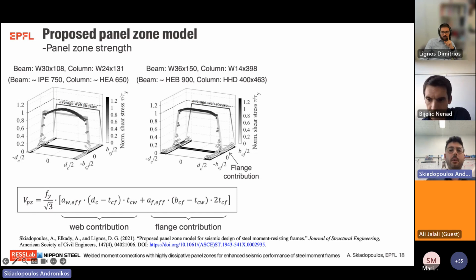Regarding the panel zone shear strength, we looked at realistic shear stress distributions in the panel zone of variable geometries, as characteristically shown by these two schematics on the top left side. What we observed is that for stocky panel zone geometries, the flange contribution, which, as I described before, is disregarded in available models, may be really considerable. Therefore, we proposed updated equations that consider both the web as well as the flange contribution. These equations were benchmarked at gamma Y, which is the panel zone shear distortion at yield, 4 gamma Y and 6 gamma Y.